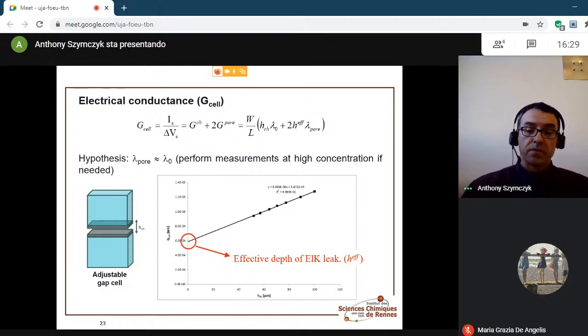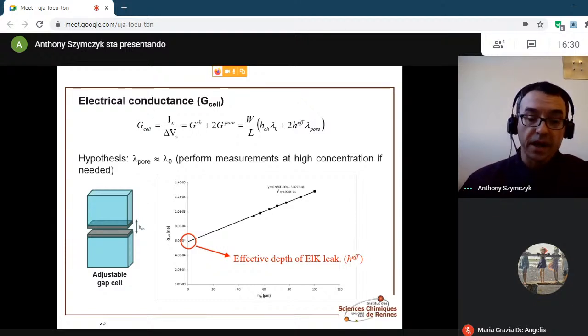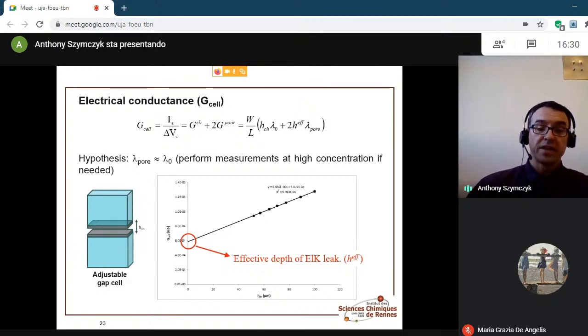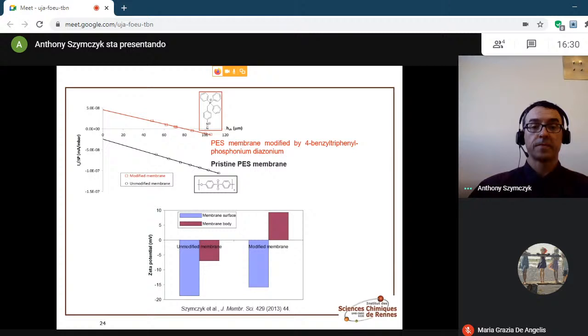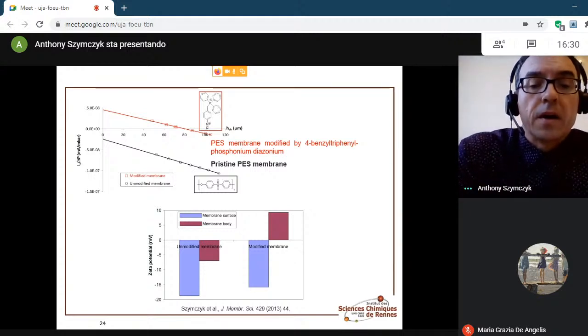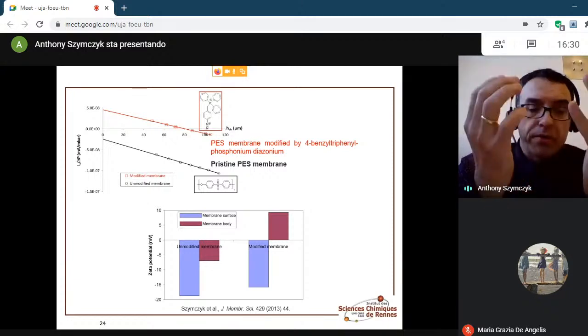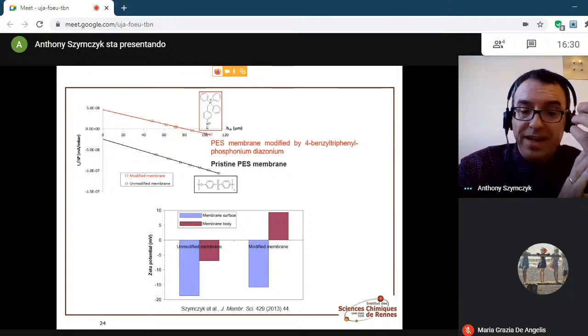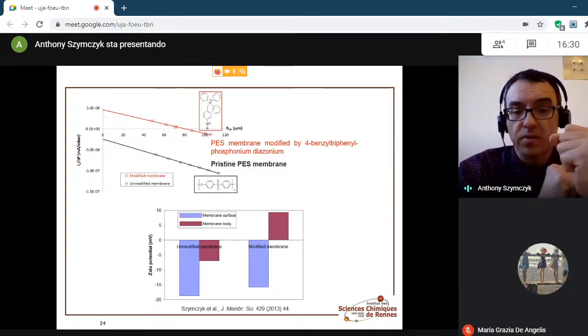Indeed, in the case of tangential measurements, the h_eff parameter, so the effective penetration depth of the electrokinetic leakage, can be deduced by an extrapolation procedure, provided that the electrical conductance of the measuring cell, G cell, is measured for different separation distances between the membrane samples, exactly as we have seen with the streaming current coefficient in order to determine the intensity of the electrokinetic leakage. In this way, both the zeta potential of the membrane surface and that of the pores inside the membrane matrix can be determined.